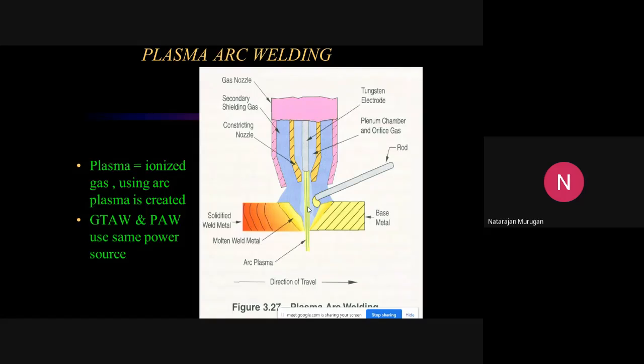So that's why metal becomes vapor, there is digging, and the mode of welding changes from conduction to keyhole mode, deep penetration mode. Please note that. This way, plasma is very high temperature and you can weld very fast, but the equipment is very costly. Even in 1998, when I called for a quotation, it was 15 lakhs at that time. So it is very costly because of the energy level.